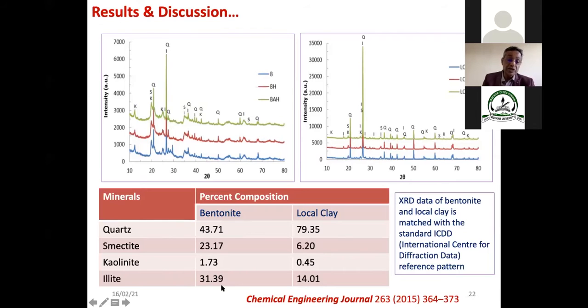Based on this, the removal capacity for heavy metals is more for bentonite, but it is less for the local clay because its quartz content, of course, is more. Our experience is that quartz is not that good for removing heavy metals.